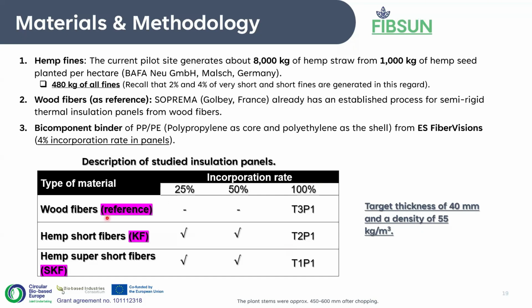And then we also investigated three batches: 25% incorporation of hemp short fibers, 50% incorporation, up to 100%. The same thing for the super short fibers. These two batches of material I previously introduced. In this case, we have a target of 40 millimeter thickness and 55 kilogram density. So this is basically a flexible insulation panel.